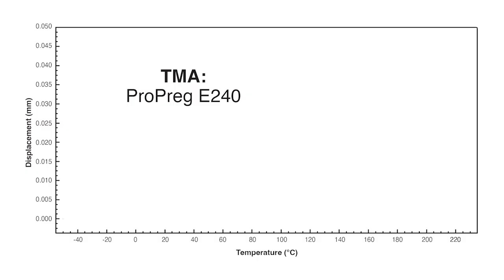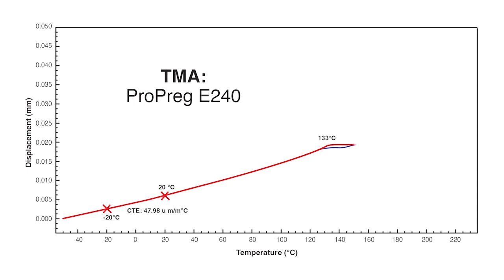As we look at the TMA of E240, you can see that before the TG, from minus 20°C to approximately 130°C, E240 has a constant rate of expansion, or CTE, of approximately 48 parts per million. As the temperature continues to ramp, you see a deflection in the curve at 133°C, indicating the TG of E240. After the TG, as the temperature ramp continues, you see a second constant rate of expansion known as the post-TG CTE of approximately 208 parts per million.